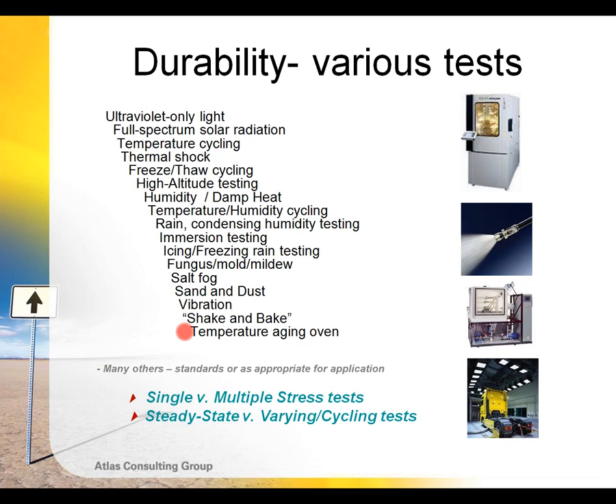The important point to realize here is that these fall into one of four categories. Some of these are single stress tests, such as temperature. Others are multiple stress, such as temperature and humidity. Of these, some are steady state tests, such as the 85% relative humidity at 85 degrees C damp heat test called for solar panels. And others are cyclic or varying tests, such as a thermal cycling test with changes in temperature or changes in temperature and humidity. So at each different level, we isolate different stresses.